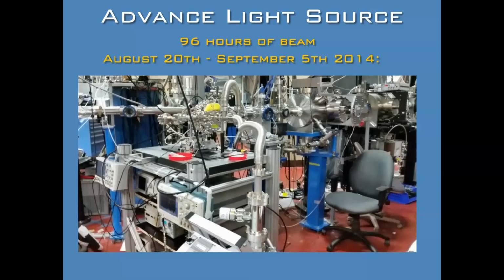And so we also had a crystal that had thorium-232 in it, which should be chemically very similar, but it doesn't have the nuclear transition. And so that was going to be our control measurement, because you shoot VUV light into a crystal, it's probably going to glow, right? And so we're getting ready to do the run and put the crystal in. And something just in the back of my mind started bugging me. I was like, what do you think the probability is that when they put the crystals back in the box, they put them in the right box? Because you can't tell the difference. One has the right nucleus, one has the other nucleus.